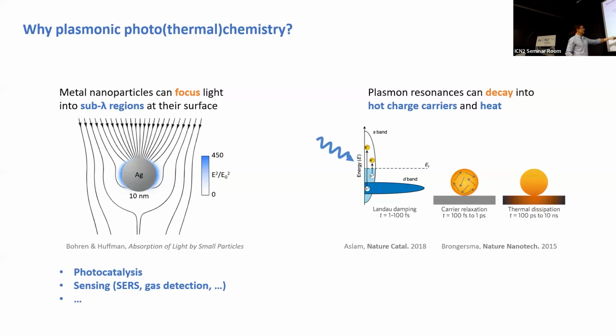The second reason is not related to what happens outside the nanoparticle, it is more related to what happens inside. So what happens when we absorb a photon in a metal nanoparticle? It kind of looks similar to what happens when you absorb a photon in a semiconductor, where you have a photon coming in and an electron from a valence band being excited to a conduction band and leaving a hole behind. Now, in a metal, something similar can happen where a photon is absorbed, you leave a hole in, let's say, the sea of Fermi level electrons, and then you excite the electron into an empty state. However, a metal doesn't have a band gap, so there is a continuum of energy levels, which means this excitation will thermalize extremely quickly. And so the timescale of this excitation is typically between 1 and 100 femtoseconds.